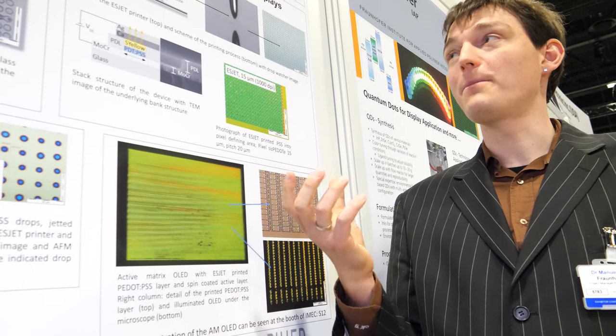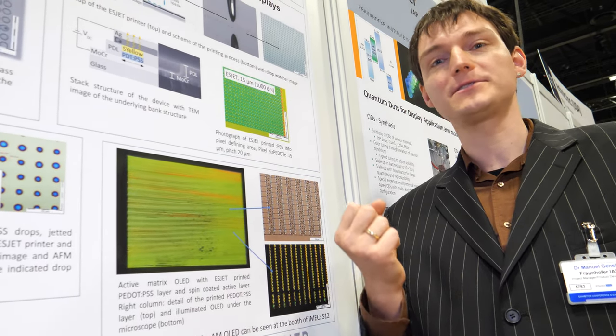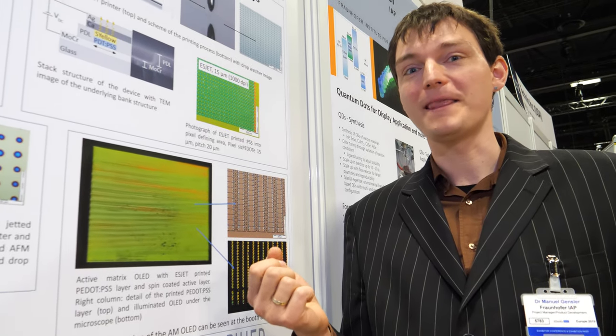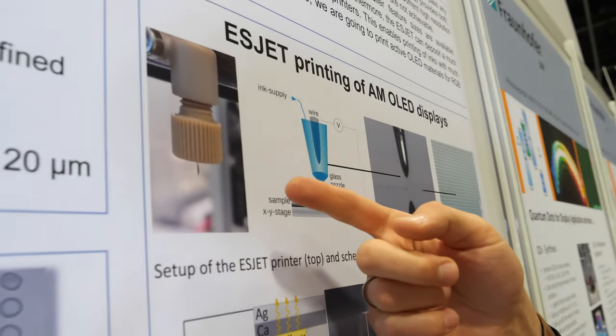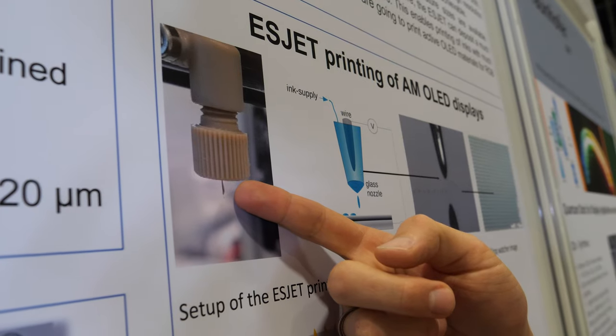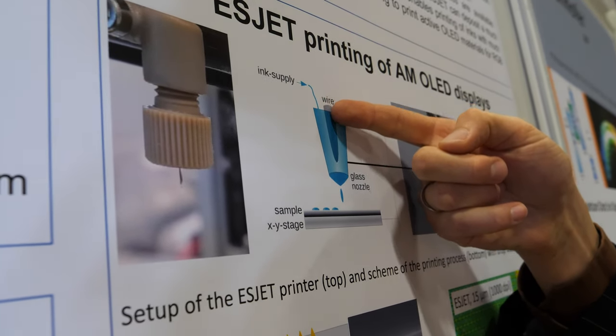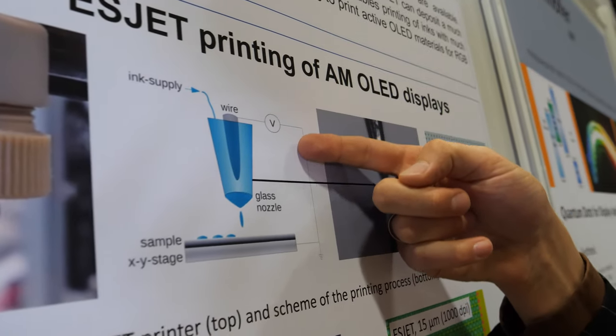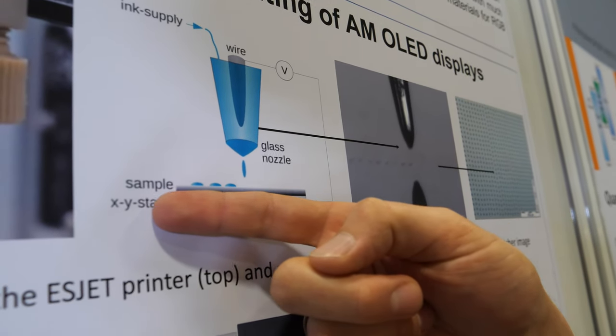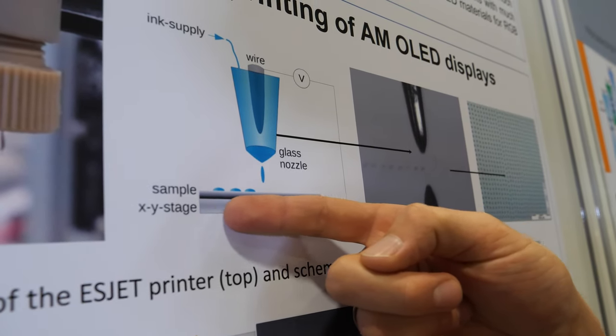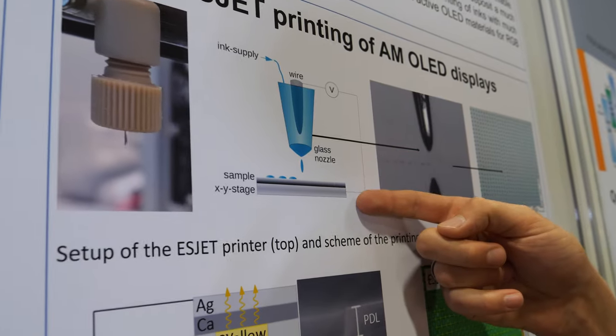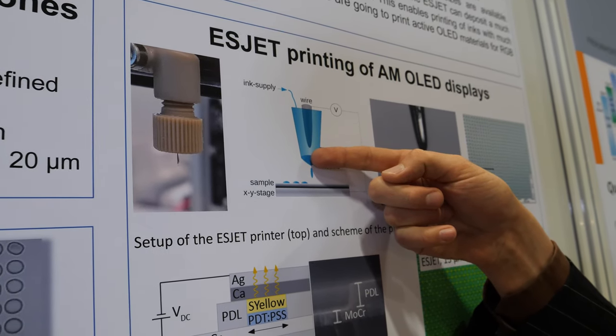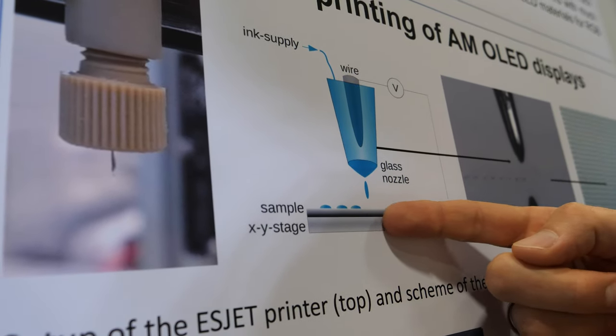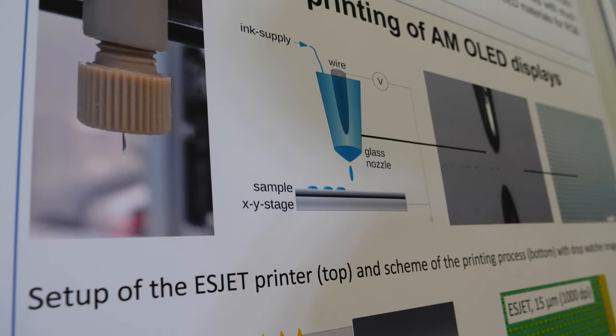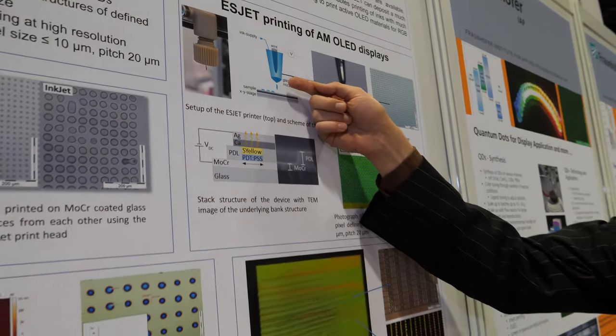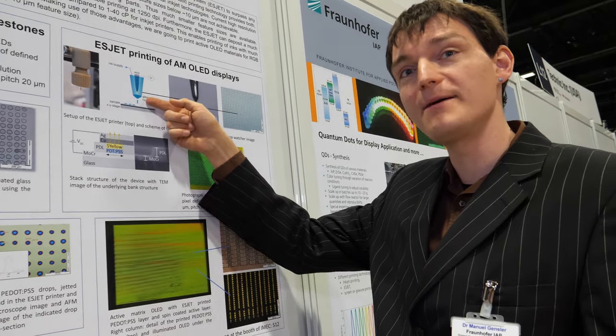we were interested in the opportunities of a new technology called electrostatic jetting, ESJET technology, which is shown above here. So we use an ultra-fine glass needle, which has a metal wire inside, and this is connected to a high voltage supply, and the counter electrode is below our substrate or the active matrix backplane. And by applying a high voltage field, we force the ink out of the nozzle through a Taylor cone onto the substrate without any moving parts, without the use of piezo, and therefore we can print feature sizes much smaller than the nozzle diameter.